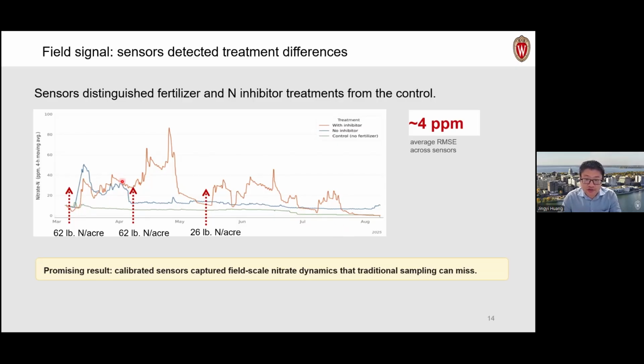Then there is the nitrogen fertilizer treatment where we do not add a nitrogen inhibitor, as you see here. In this case, the nitrogen level initially jumps after you put the fertilizer. Then later on, it quickly disappears, either by uptake by the plants or leaching downward. Then if we add some nitrogen inhibitor over here, we can see that over time during the growing season, the nitrogen level in the soil remains relatively higher as compared to the other two plots.